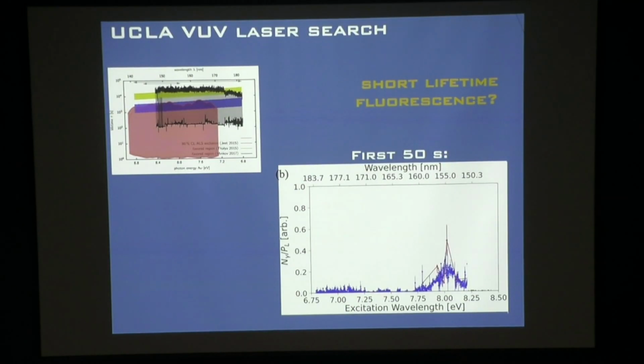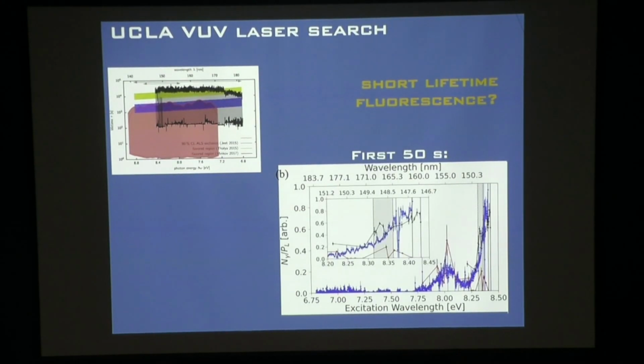And then as we got down to around 8.3, 8.4 eV, we started to see this short lifetime signal going up and up and up, and we just couldn't really tune our lasers past here without a lot of modification. And so we stopped there. And if you zoom in here, we then put in another thorium-229 crystal, and we saw a similar behavior. That's this black curve. Whereas the 232 really didn't show anything here at the level of our signal to noise.